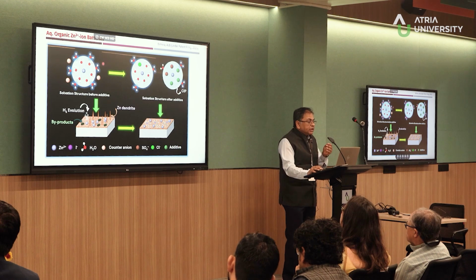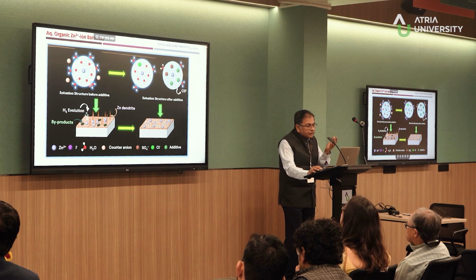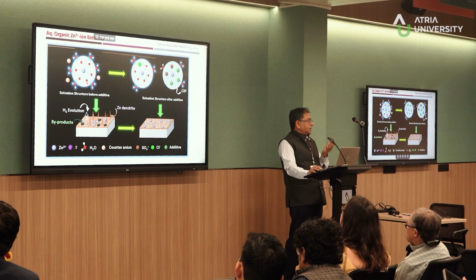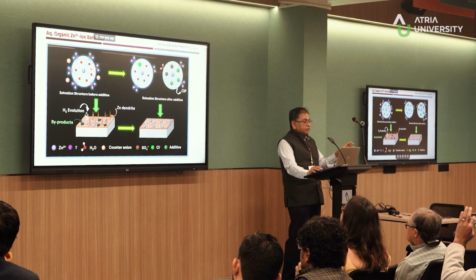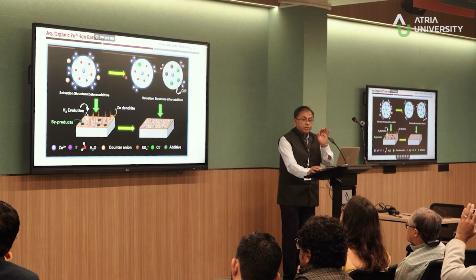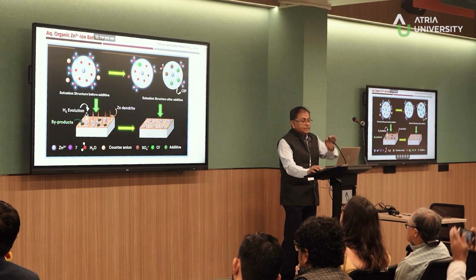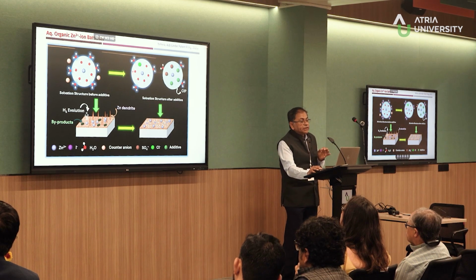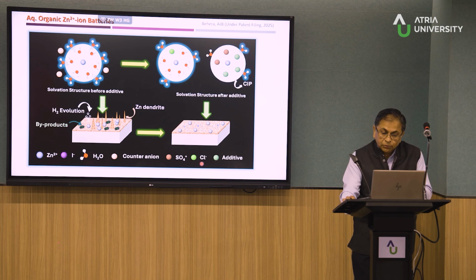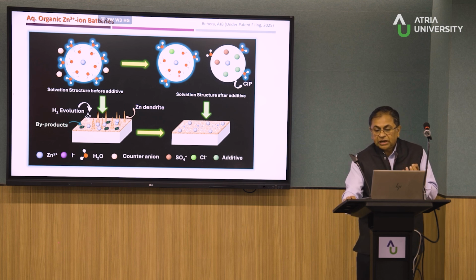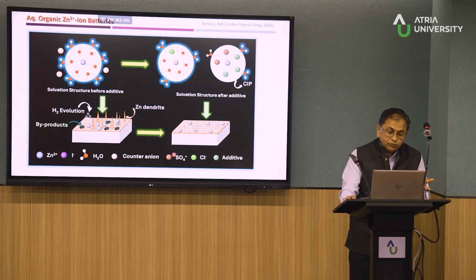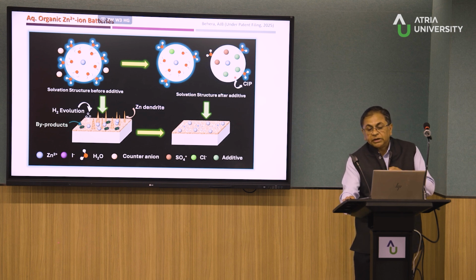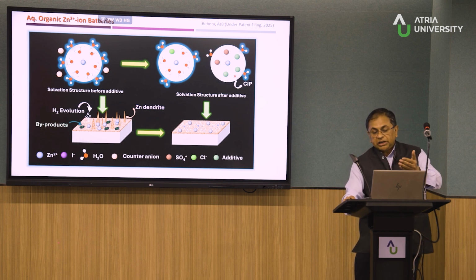Okay, so let us say you start with a very classic zinc coordination of hexa-aqua in the bulk. Okay, with some additives, again depending on the counter anion. All right, you can tweak the hydration in such a way. So we have an additive here. In one particular type of anion, which is, let's say, chloride, you'll have a hydration shell like this, or if you move to a sulfate, you'll have a hydration shell where now the additives are actually coming into play. All right.